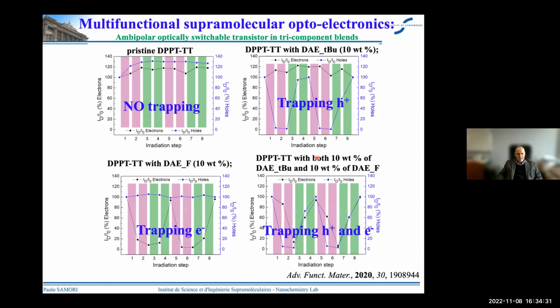pre-patterned chips. And here in this cartoon, I want to show you how we can study the light responsiveness of our material. We start from the pristine polymeric semiconductor. You see that by making cycles of UV and visible light, there is very little response to the light stimulus. Then if we add the tert-butyl diarylethene, so we blend the semiconductor with the tert-butyl diarylethene, we can see that there is only a response to the, let's say, hole transport, by doing cycles of UV and visible light emission. So we are triggering uniquely the trapping and detrapping of the holes.